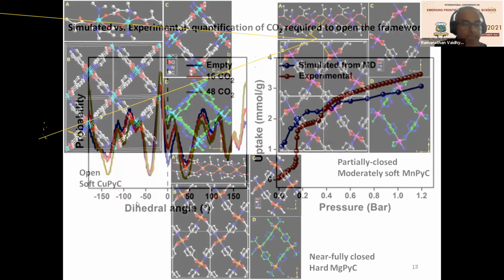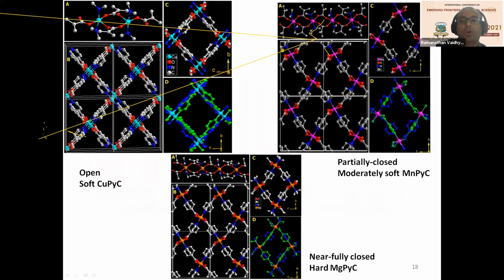Okay? Now, how did we gain control on this gating? We made three different MOFs, the exact same structure, but three different MOFs. All are isonicotinates. One is made with copper, one is made with manganese, and then we have the parent one, which is with magnesium. Now, if you carefully look at it, magnesium is a very hard center, whereas the pyridyl is a borderline soft acid. Manganese is a hard center, but not as hard as magnesium. Manganese 2+, magnesium 2+. Whereas copper 2+ is very soft, so it matches the pyridyl much better in terms of softness. Now, this is the systematic approach we adopt.